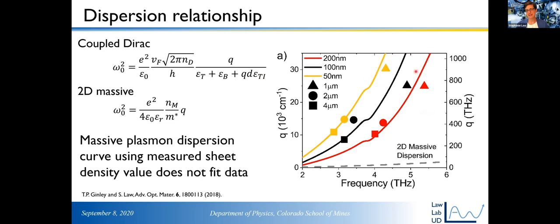We have a systematic offset here for the smallest stripes. What we think has happened is that we're ion milling to make the stripes. So we think the edges of the stripes are suffering from fabrication damage. And so the stripe is probably actually thinner than 1 micron. We don't know how much thinner, so we did not adjust the wave vector. So this match is really pretty good.